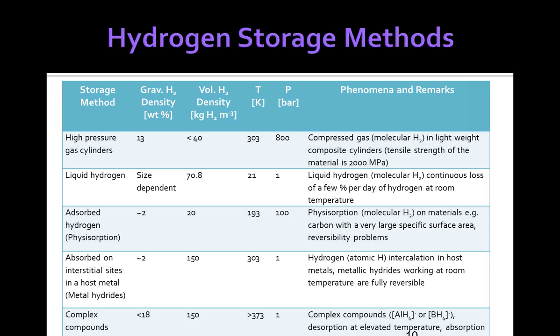The problem with this is compressed gas in lightweight composite cylinders. You need to develop specialized cylinders to store this hydrogen, like Kevlar composites and other materials. Liquid hydrogen is size dependent, but it stores about 70.8 kilograms hydrogen per cubic meter, stored at 21 Kelvin, the liquid hydrogen temperature, at 1 atmosphere. The problem with this is it's very expensive.